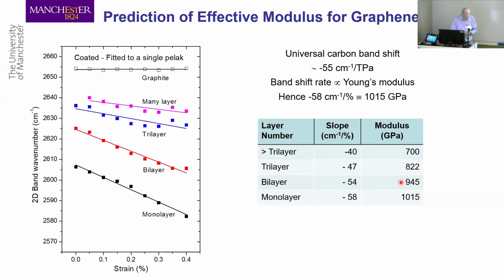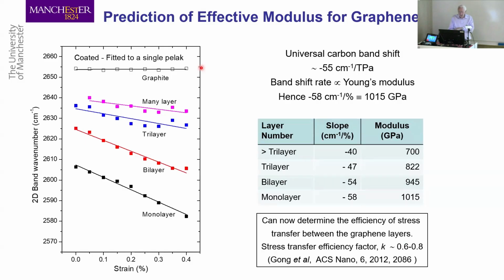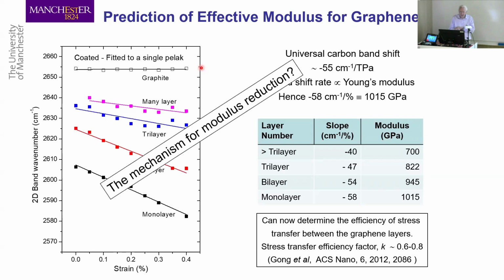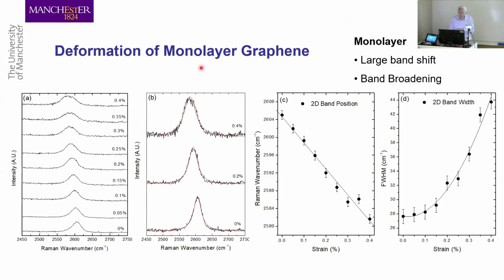And that's a sort of funny effect, but probably makes sense because by the time you get to graphite, which has got loads of layers, the stiffness in this particular experiment is very low. And we can actually show that what you need in this case is stress transfer between the different numbers of layers. What is this mechanism for the modulus reduction? Well, let's look in detail at the plots, and it's a little bit in detail, but quite interesting.